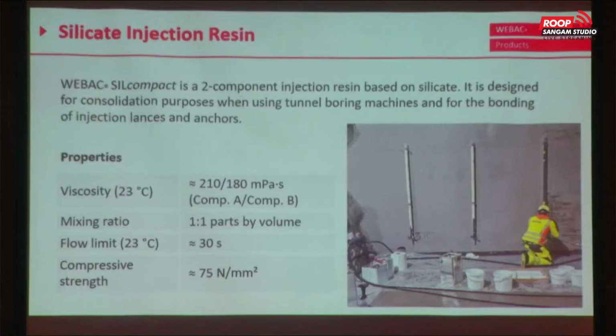Here we did some tests where we anchored overhead. There's a thixotropic version, so you pump it overhead, and if you stop, the material stops. It will not flow downwards again. So as long as you're pumping, it flows, but if you stop, it stays. The material itself delivers a high compressive strength, 75 Newton per square millimeter, which is a great material for anchor bonding, for example, or for soil stabilization or loose rock stabilization.